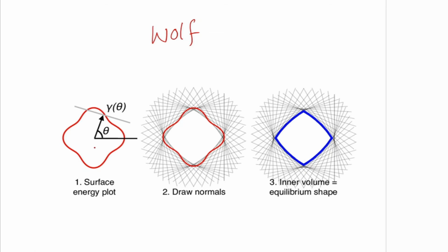So now what is done? This is one such plot in 2D that I've drawn. This is an even better way of drawing it. These are your 1, 0 directions. So to do a Wulff construction, what you do is very simple. You draw a vector. Suppose it lies at a point P, and this is O. So OP is a vector, and OP is telling me one of the crystallographic directions. It can be any direction. If you draw this way, suppose this is OA; OA for me is a 1, 0 direction. For OP, in general, the direction is HKL, and each of these are Miller indices.